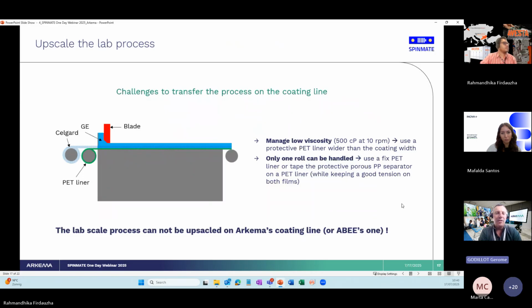So the automation has been made for the impregnation of the porous PP. Now we think about how we can do that on a coating line, because the process is not the same. At lab scale, on the coater, you have a fixed liner and the blade is moving during the casting. On the coating line, it's the opposite. You have a fixed blade, because in our case it's a coating line with a blade, and the liner is moving. So the only thing we could think of is to have a roll of Celgard moving and passing through the tank of gel polymer electrolyte and being impregnated that way.